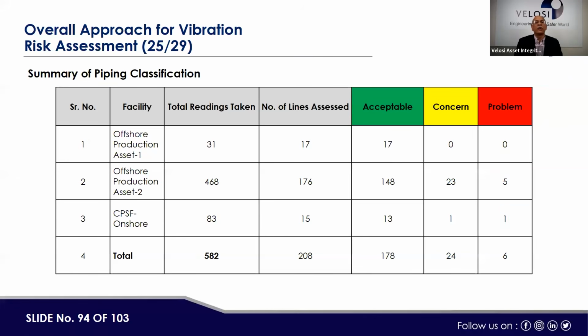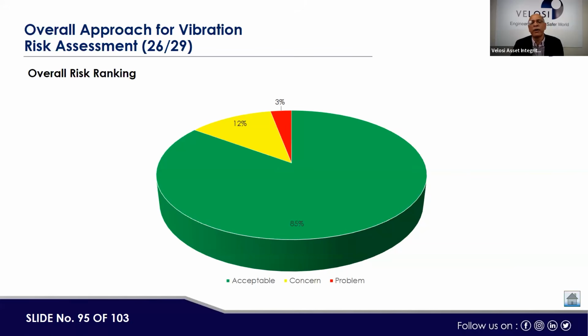Then total readings taken were 31 from the facilities point of view, and all 17 were acceptable, no issue; the number of lines assessed was 17, and acceptable 17, concern 0, problem 0. Whereas the offshore production asset had 23 with concern, 5 with problem. The CPSF onshore had 1 concern and 1 problem. Altogether, 24 lines were observed with concern, where corrective action was required, and 6 were observed with a problem. So if you see, 85% of the piping was okay, 12% was with concern, and 3% was with problem, and that is the overall.